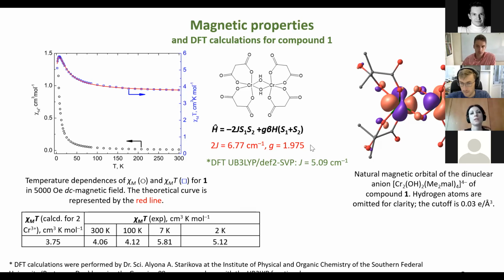To confirm the obtained magnetochemical data, we performed DFT calculations for this compound. As evidenced by the shape of the natural magnetic orbital of the dinuclear anion of compound 1, an antiferromagnetic exchange channel is absent, resulting in the appearance of ferromagnetic interactions between 2 chromium centers. The estimated J value is in agreement with the magnetochemical data.